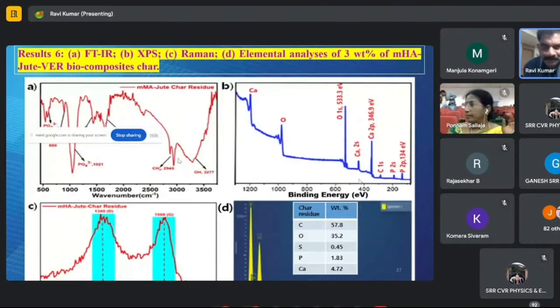Also, we checked the char with FTIR, XPS, Raman, and elemental analysis. We found different elements on the surface: calcium, oxygen in the different phases of 1s, calcium 2s, and different phases of Ca 2p. This is the orbital structure of XPS. And FTIR also shows CH2 groups, OH groups, and phosphate groups. It means the phosphate group appears even after charring, even after prolonged heating, the phosphate is strongly protecting the surface. This is the evidence from FTIR: the peaks show calcium and phosphate very clearly, and CH2 groups and OH groups appear very clearly, and the peak intensities are very high. It means this is strong enough to protect against heat.